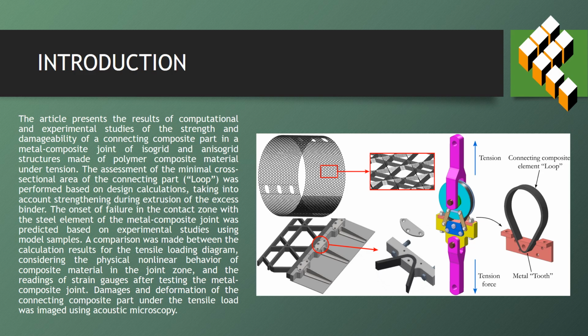The onset of failure in the contact zone with the steel element of the metal composite joint was predicted based on experimental studies using model samples. A comparison was made between the calculation results for the tensile loading diagram, considering the physical nonlinear behavior of composite material in the joint zone, and the readings of strain gauges after testing the metal composite joint. Damages and deformation of the connecting composite part under the tensile load was imaged using acoustic microscopy.